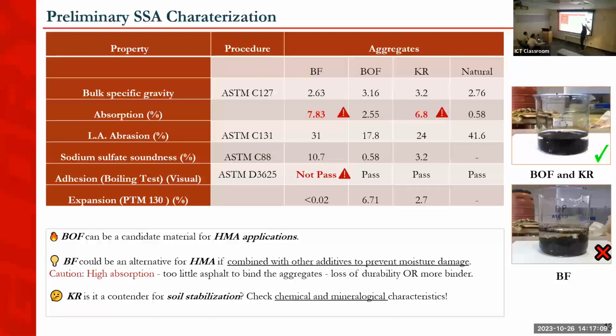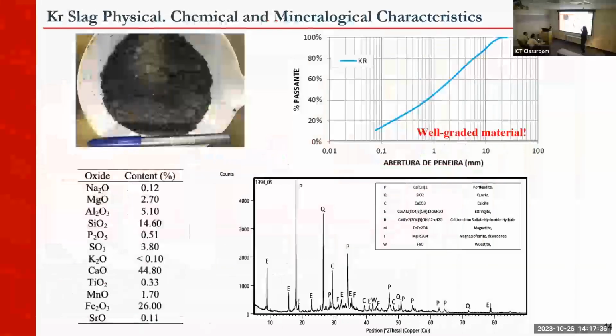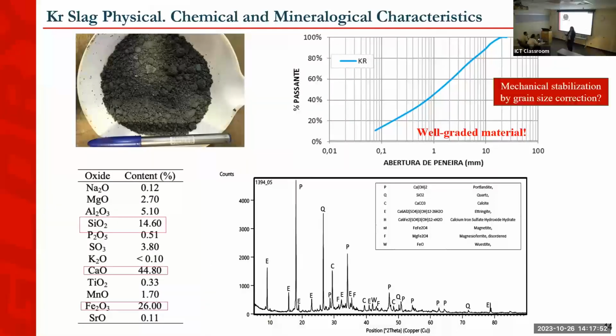And KR, same thing we observed in terms of absorption. When we started this research with KR in Brazil, one of the concerns from the company was with the KR slag. They had huge piles and no use. They were going to landfills. So we started to focus on the KR slag when we started research on slag use. So we went a little bit deeper on the KR and we did a size distribution analysis. We saw, well, this material is well graded. Maybe it can act like a rock and we can stabilize soils by mixing soil with aggregates, or mechanical stabilization.